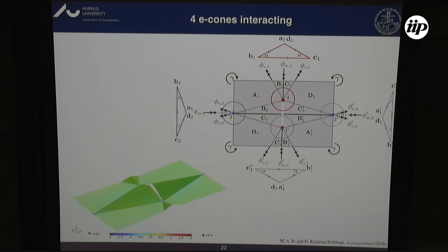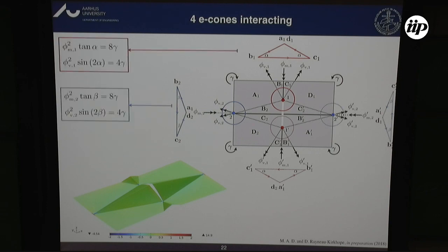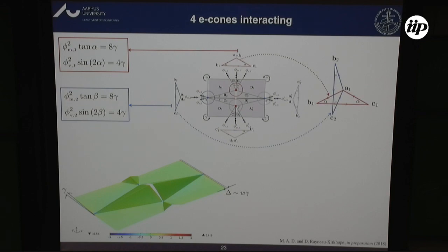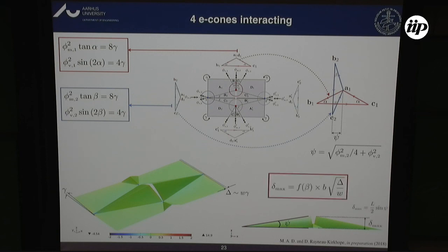So we use this system to do some high school geometry, because this is all on the plane, and we can relate the out-of-plane deflections of the structure by just measuring distances on a unit sphere. It turns out nicely that we get the same scaling that we derived from the continuum model, which is given by the square root of the amount of deformation over the width of the sheet.